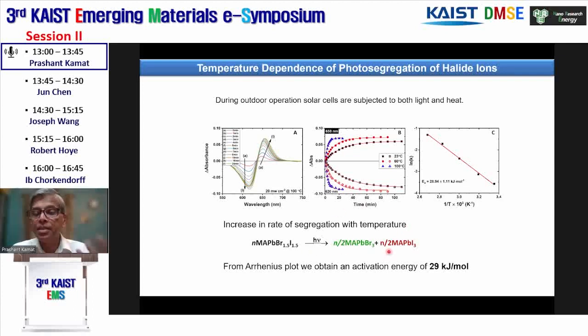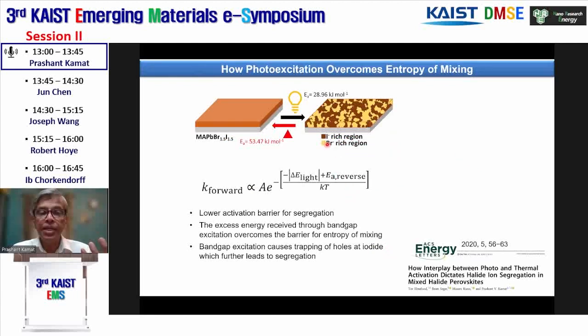So how to consolidate the two? What I've told you is there is an activation energy in both processes. So the preferred phase is the mixed halide phase in the dark, but only when you put light, that is an extra energy that needs to overcome this barrier. And in addition, there is also another barrier. So here we can write the k forward, that is to segregate, is proportional to the difference between the EA reverse and EA minus delta E light. So this one needs to compensate for the mixing of the two.